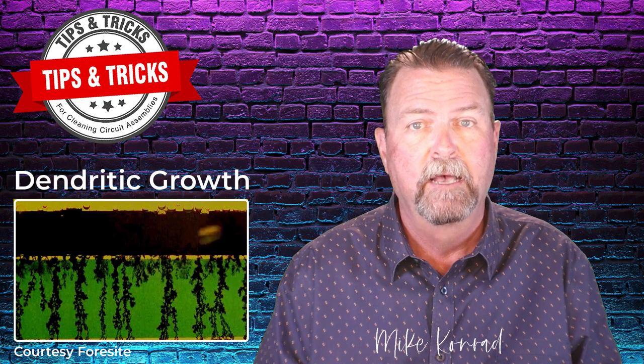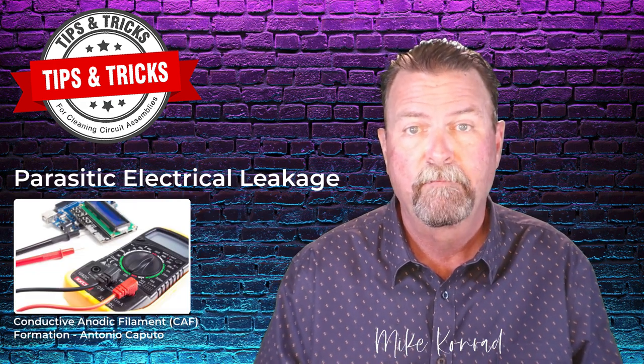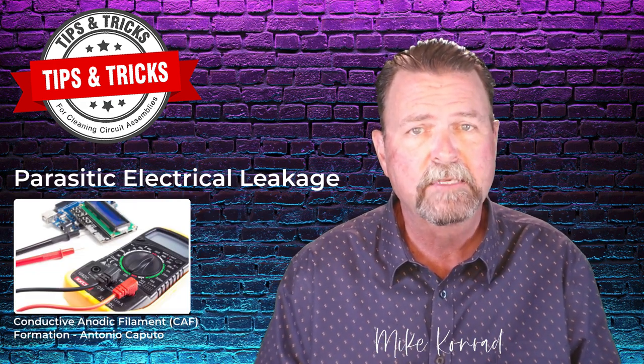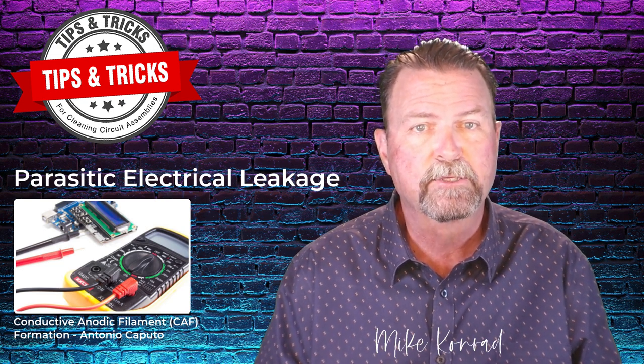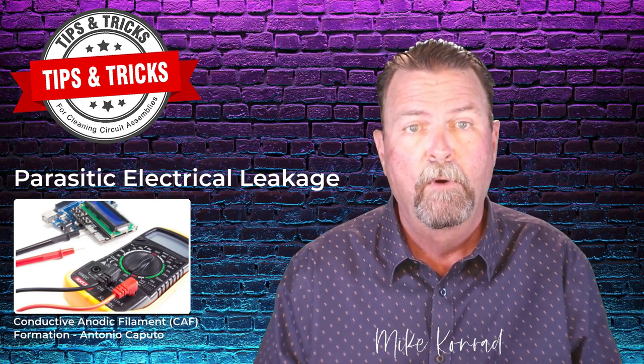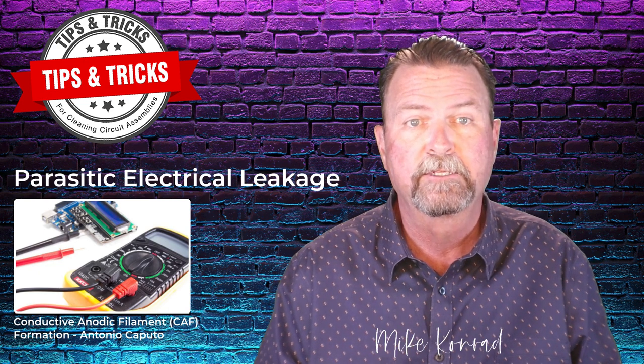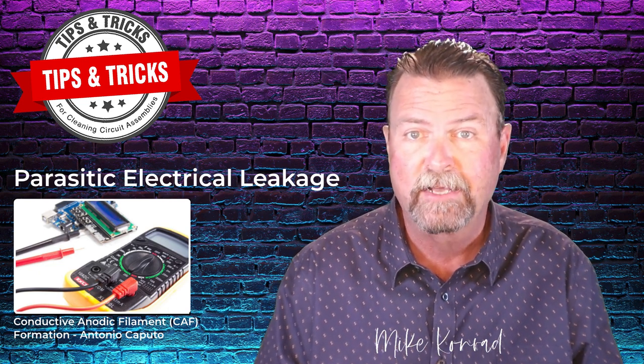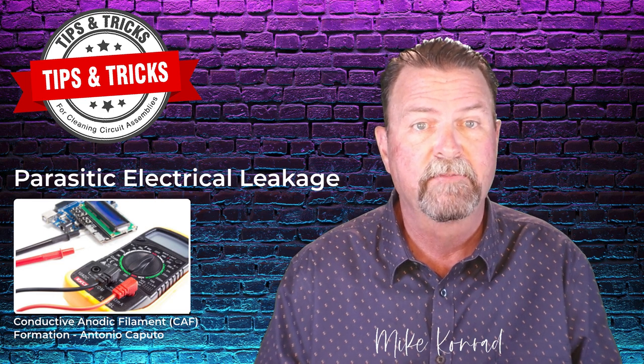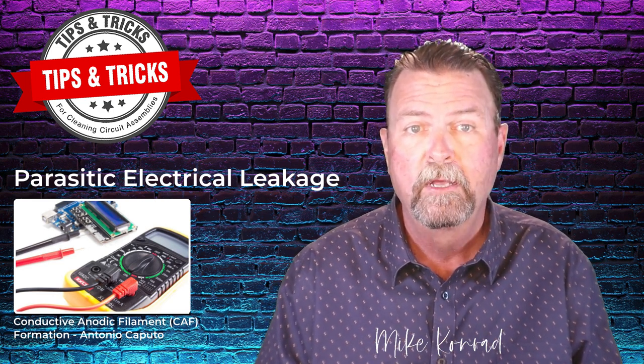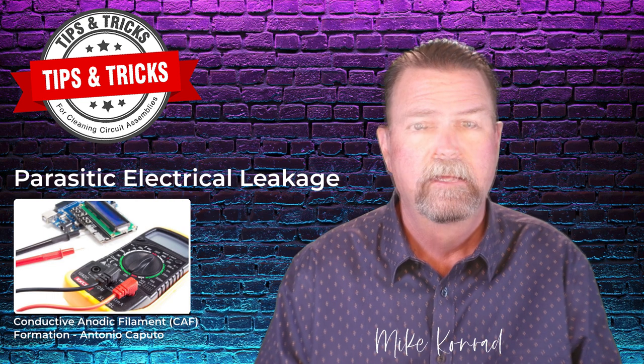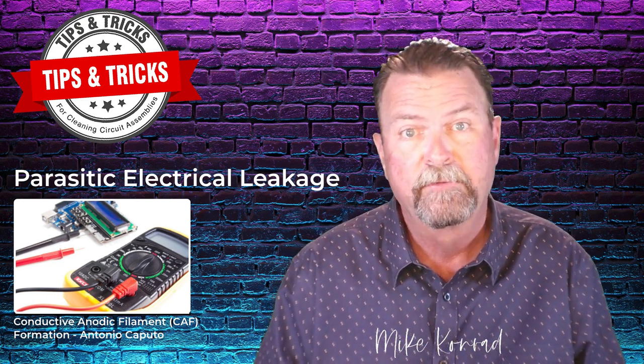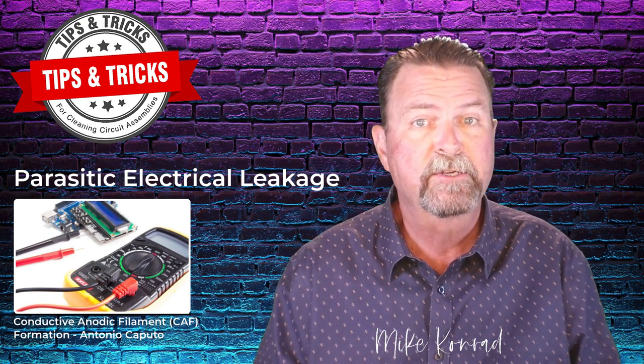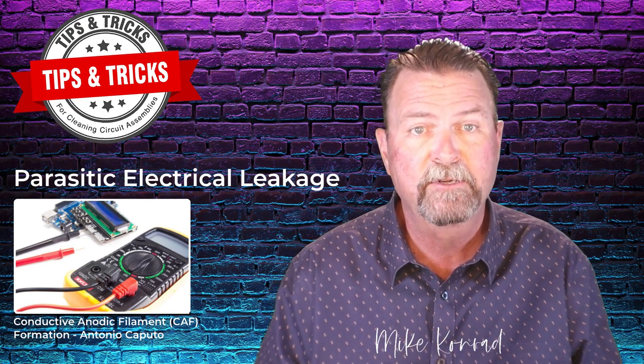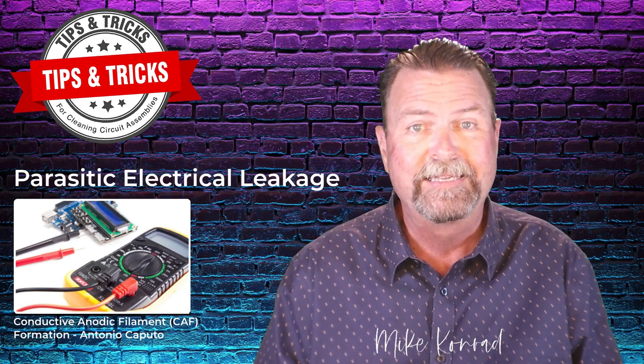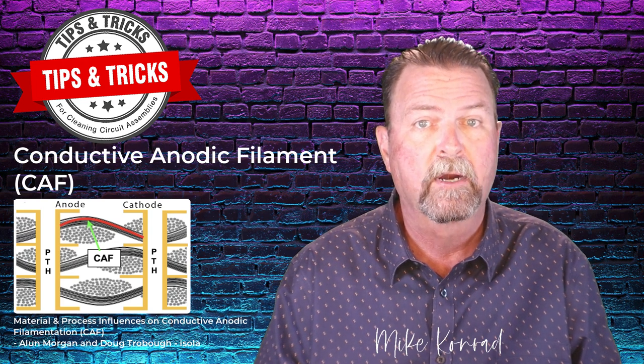The second form of ECM is parasitic electrical leakage. Parasitic leakage is not commonly visible. It lacks a visible metal structure found in dendritic growth. While parasitic leakage does not normally lead to a dead short, it does, in effect, reduce the dielectric properties of the laminate, allowing some current to flow between the anode and the cathode. This could lead to rapid battery drain if the board is operated with a battery, or situations which may cause the assembly to malfunction. The third form of ECM is conductive anodic filament, or CAF.